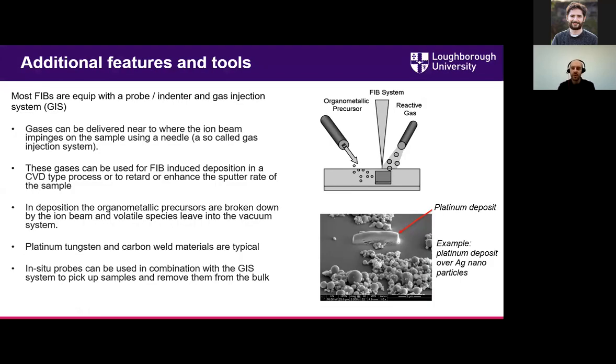So our next tool that we have is to be able to flow precursor gases into the chamber. These precursor gases can be broken down by the ion beam or the electron beam and essentially deposit a metal on the surface. This is particularly useful for protecting samples. So if we want to prepare a TEM sample, we would protect the area with platinum or tungsten. And we can also use this for welding onto probes, so we can use this as a way of picking things up and moving them around. Some of the gases that we flow into the chamber can also be used to act as an etchant. So we can increase the sputter yield of materials by flowing a gas across the surface.